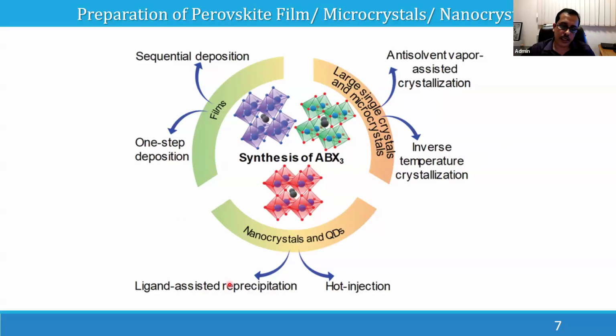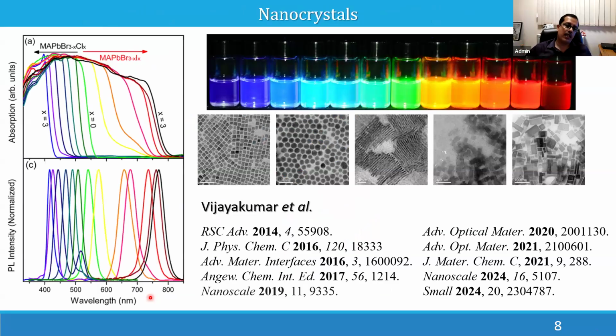For nanocrystal synthesis, we use ligand assisted reprecipitation, which is commonly used for chalcogenide based nanocrystals like cadmium selenide and cadmium sulfide systems, or hot injection. You heat the reaction mixture and quickly add one reagent to it, and suddenly the nanocrystals will start forming, and you can precipitate, take out, and centrifuge to get the nanocrystals and quantum dots. And these are the nanocrystals that were made, and these are the absorption and emission properties.